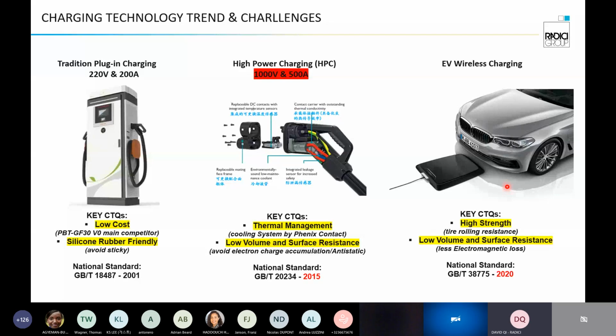Now, these standards are not fully established yet, and we are cooperating with several tier ones and also OEMs to try to fulfill the materials requirements within these regulations, because this part needs to generate an electromagnetic field, and you need to pay attention to materials with much lower resistance and also higher dielectric strength, because this could affect the electromagnetic field and thereby the charging performance.